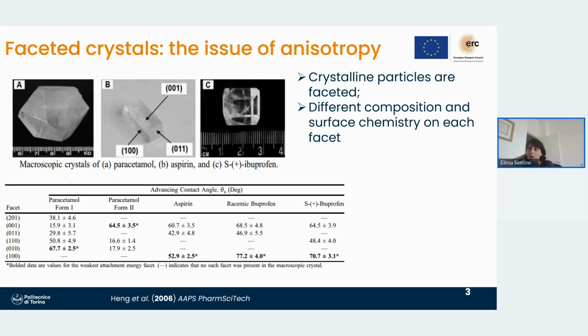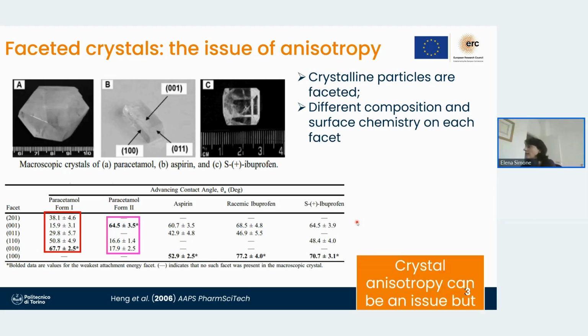Now, this has been shown a while ago by Jerry Heng at Imperial, who measured the water contact angles, so how hydrophilic were different facets of paracetamol form 1. We can see that different facets show different wettability because of the different groups of paracetamol that are characterizing each facet. If we change polymorph, we can also see different surface nature, and again, different molecules also show anisotropy. Now, because I design crystals, I define myself as a crystal engineer. I can actually use this anisotropy if I am able to understand well how surface properties are related to crystal structure to actually design particles.